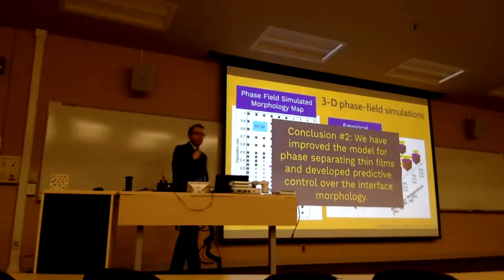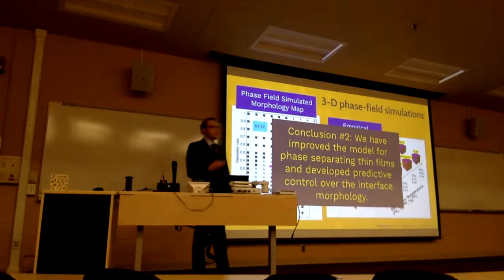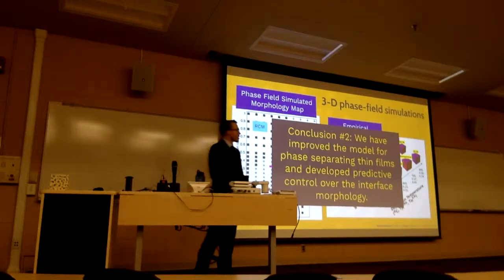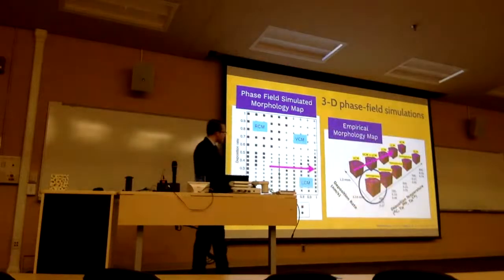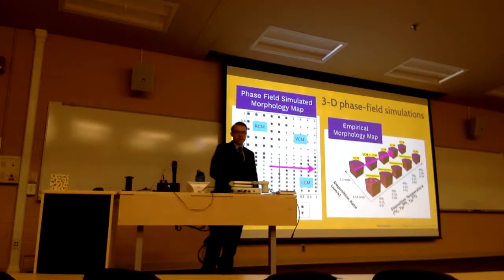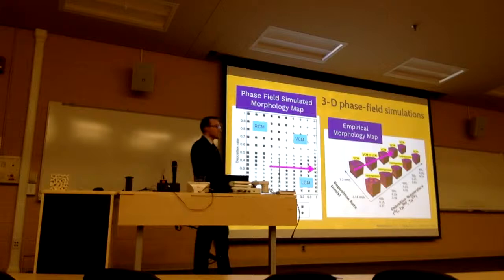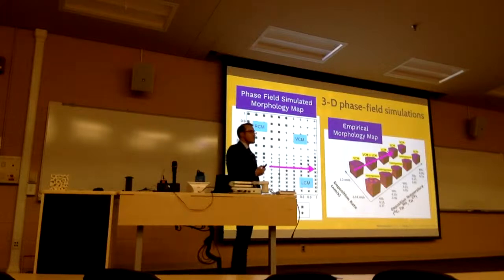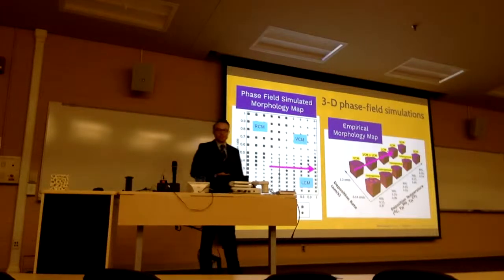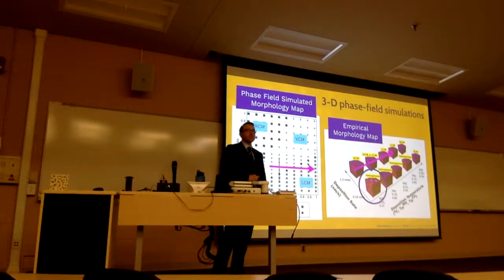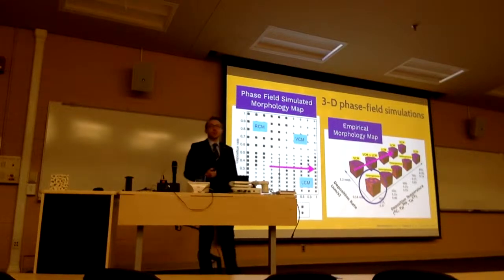So the second conclusion we can make is that we've been able to improve the model for phase separating thin films and design some sort of predictive control over the interface morphology. One thing I've kind of been hiding from you on this experimental morphology map is that we see a completely different morphology at the lowest deposition rates we experimented with in this study. You can see that it's actually not a homogeneous-like morphology, but in fact hierarchical or heterogeneous. And that's where I want to go next.